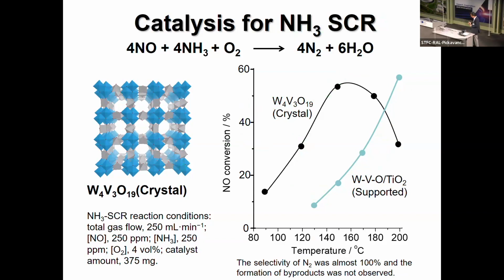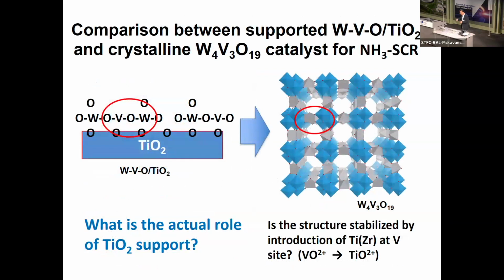But very unfortunately, the material shows a decrease of the activity when you apply higher reaction temperature. In other words, the material is not highly strong against high temperature. That's the pity. The material is quite nice, but it's very unstable. That happens in many cases, but we need to overcome it. We have to stabilize this material. How can we do this? We have been thinking for many days how to improve the thermal stability. I was not able to get a clear answer to it. But one day I got an idea.